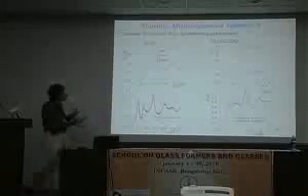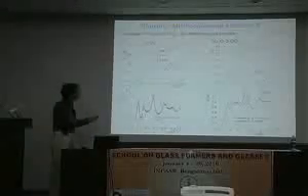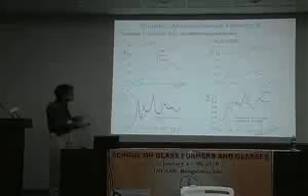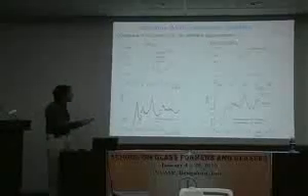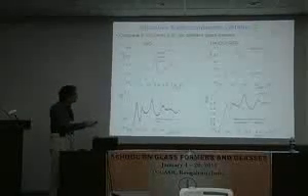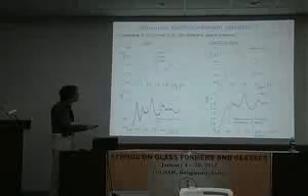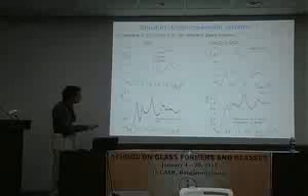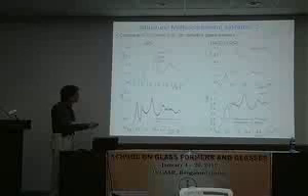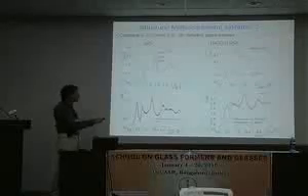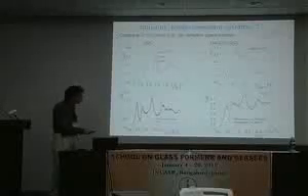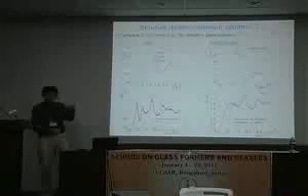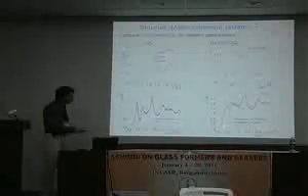Now, if you put in a little bit of sodium in the system, here things really can get complicated. So again, here I'm showing a computer simulation. Sodium disilicate, this is the partial structure for oxygen, and here for sodium. What you see here is that around 1 inverse angstrom, you see a quite nice peak in the sodium correlation. You let it run through this machinery, so you have 6 partial structure factors. This very nice peak here hardly shows up here. If you have a problem with your resolution, you do not see this peak anymore.